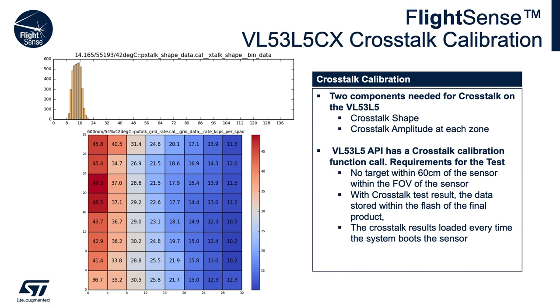With this, you can see that the crosstalk is as high as 45 kilophotons per second and as low as 10 kilophotons per second. So with knowing both of these information, we can then know that this crosstalk is always coming because of the cover glass, and we can subtract this out from each individual histogram on the part, giving you then perfect results every time you do ranging.